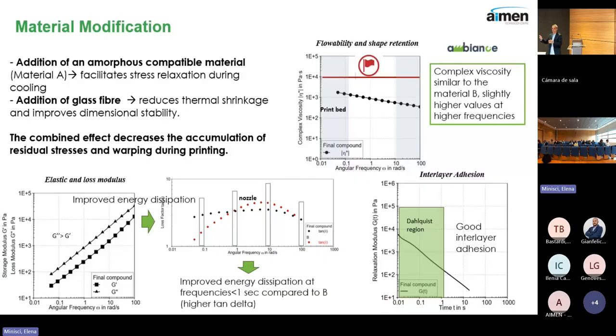mimicking what's happening inside the extruder. So we need low viscosity for the material to flow. When we go to low frequencies, it is what happens when the material exits the nozzle. And here we require high viscosity for the material to be able to maintain the shape. Of course, this viscosity at the exit of the nozzle should not be too high, because otherwise we could have issues with plugging, and this is not ideal, of course. But what we got with this material is very nice. We are within the limits of viscosity, and we are getting this nice shear thinning effect.